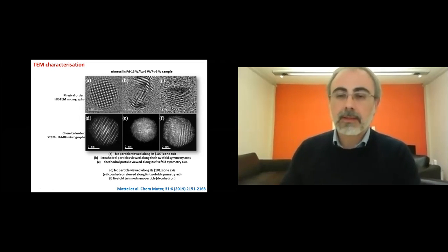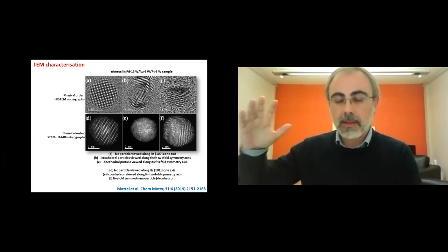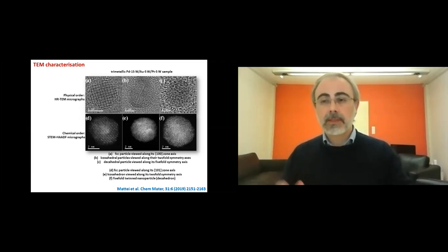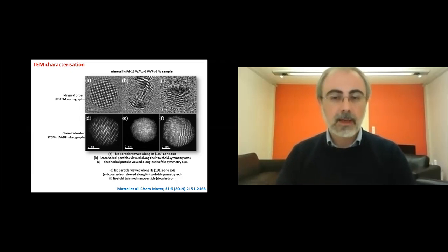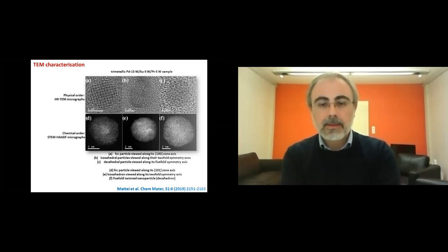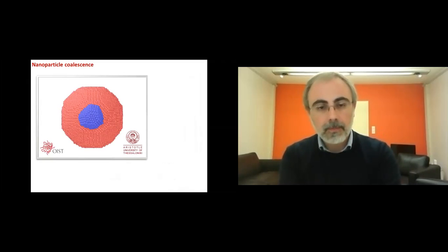And the reason for that is that the particles, as they go in the main chamber where they're deposited on the support, are quenched. So if they haven't reached some thermodynamically stable structure by then, they are stuck in some metastable configuration. And since their sizes are mostly bigger than the simulated ones, it takes longer to reach the equilibrium.